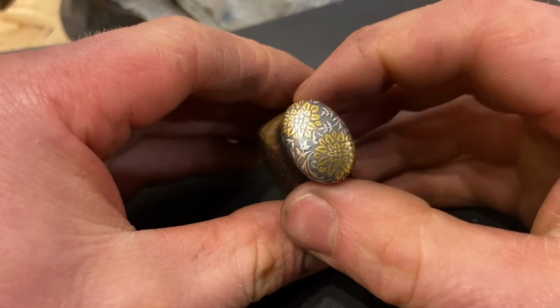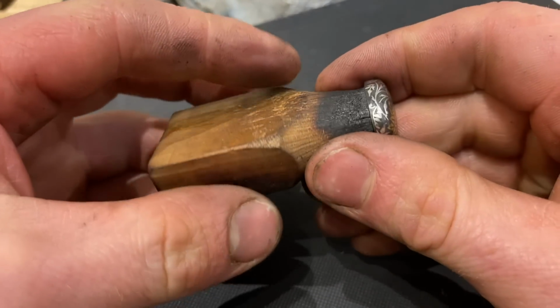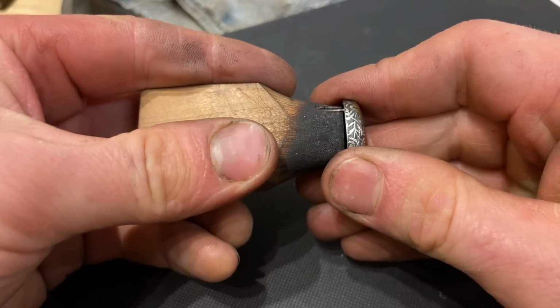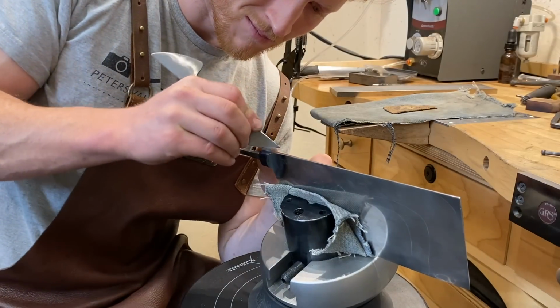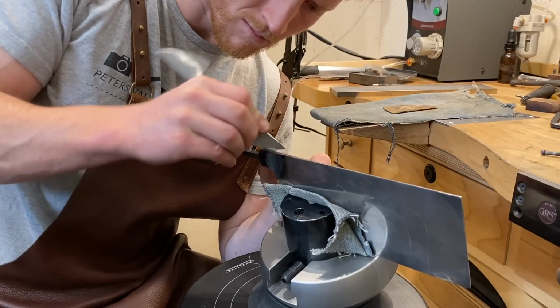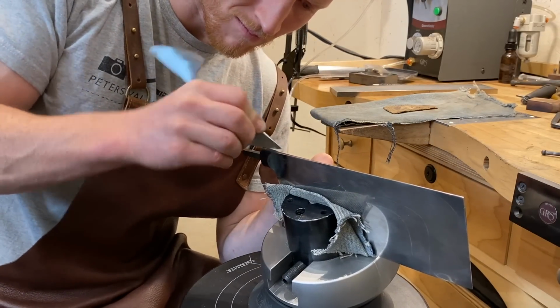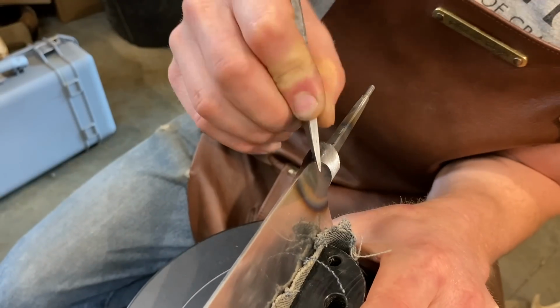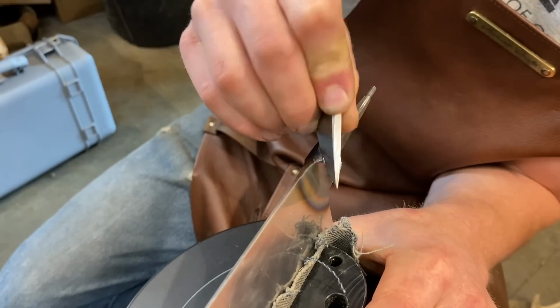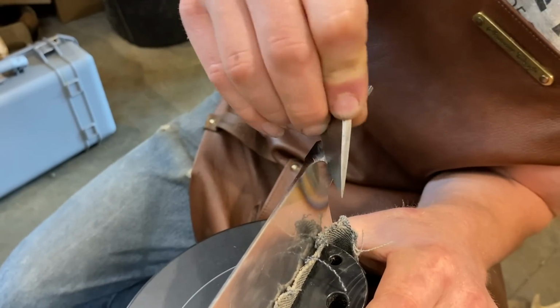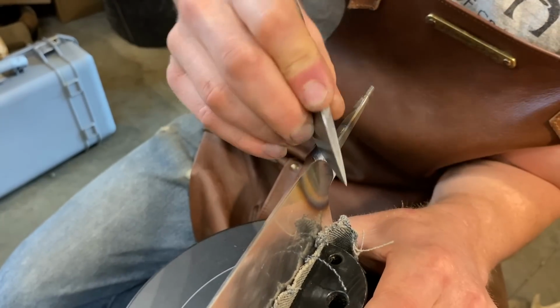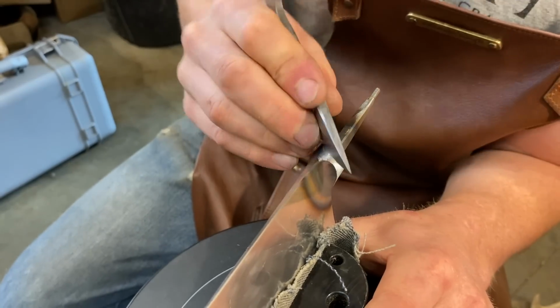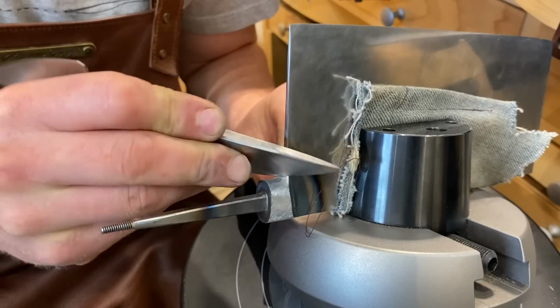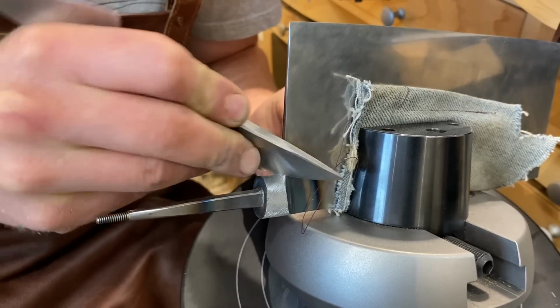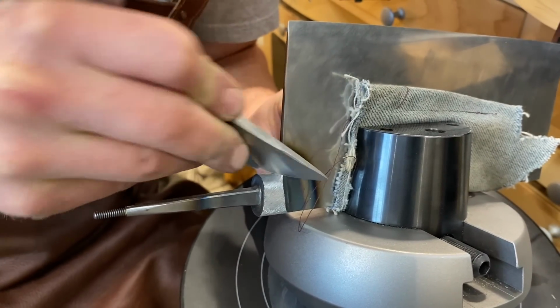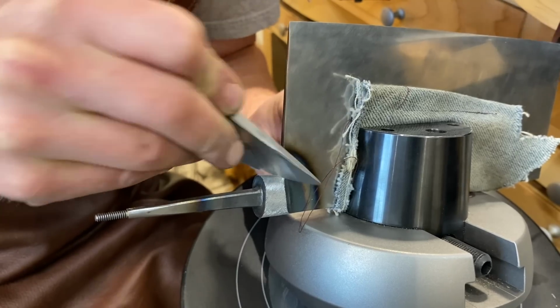I'm finally satisfied with this pattern, so now all I need to do is replicate it on the front bolster. Even after annealing this bolster with a torch, the high-carbon damascus is still quite a bit harder than the mild steel for the rear bolster. It means that the knife squeaks rather loudly as I crosshatch, and it also needs to be sharpened much more frequently. Despite those challenges, I still managed to get a beautiful, consistent crosshatched surface.